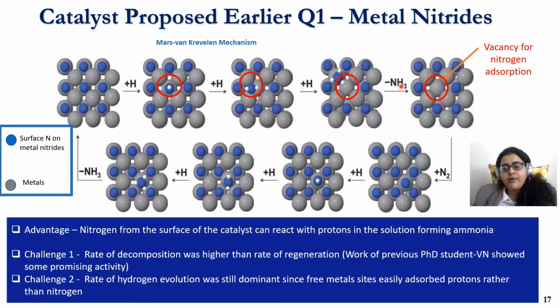Now this ammonia will be released into the electrolyte, creating a vacancy in which another nitrogen can be absorbed and protonated, and this process should go on and on. And this also has its own challenge. If the rate of decomposition is higher than the rate of regeneration, it will basically utilize all the catalyst and the reaction will stop after a point of time. So my focus was to develop a material which could make this process more stable. And that is what we tried to do.